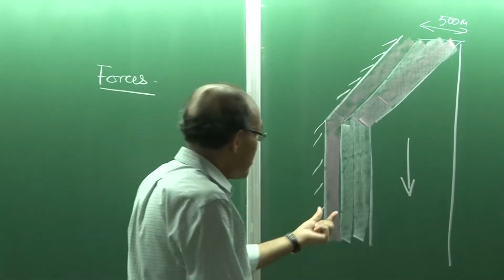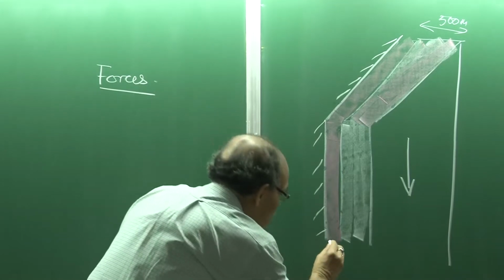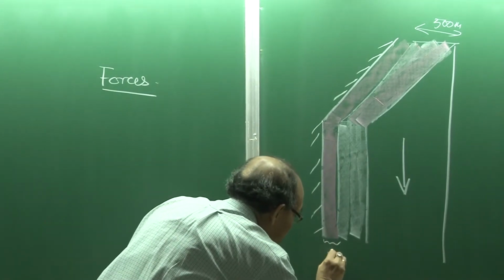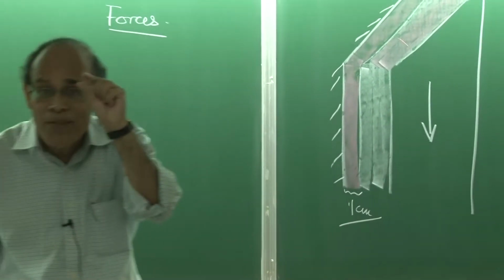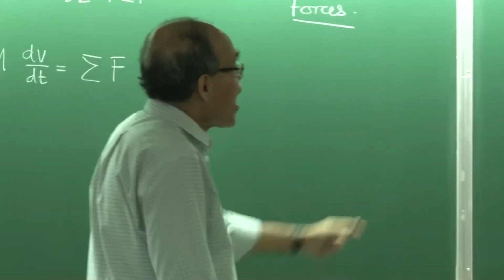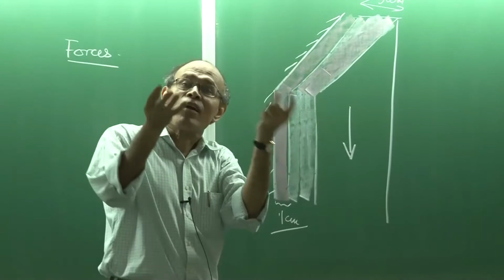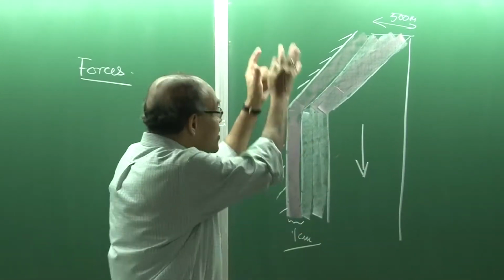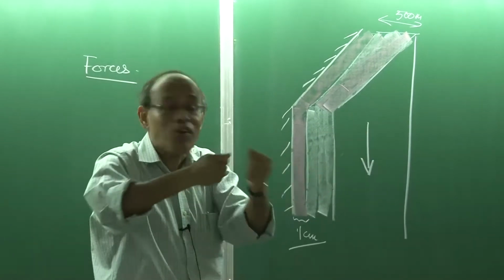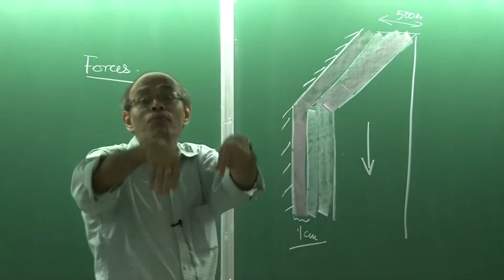What is the distance here? We are talking about a film of about 0.1 centimeter, that is of the order of 1 millimeter thickness. That is the film which acts as a lubricant. So we add solid powder. That solid powder has a low melting point. Because of the heat available, it melts, and the entire thing is moving, and the expansion and contraction creates the space. The film flows inside.